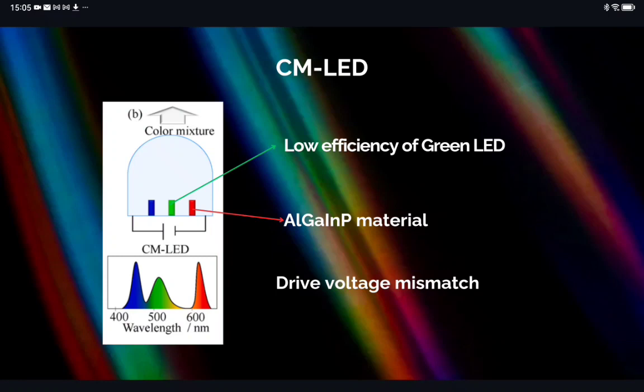Furthermore, indium can cause internal polarization. Internal polarization can move the electron and hole to the two opposite sides of the quantum well. As a result, the recombination efficiency is reduced significantly. The active region of the red LED is composed of aluminum gallium indium phosphide material, which possesses a high surface recombination velocity and, together with a long carrier diffusion length of approximately a few microns, makes the non-radiative surface recombination more significant. Aluminum gallium indium phosphide possesses some properties that do not allow the material to be used effectively as a light emitting diode.